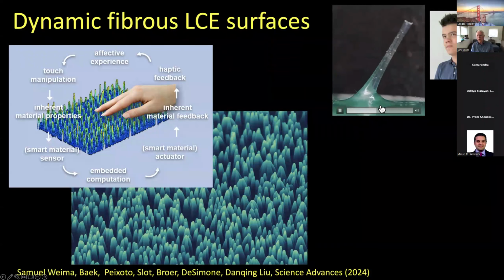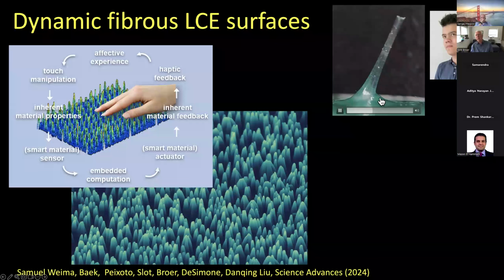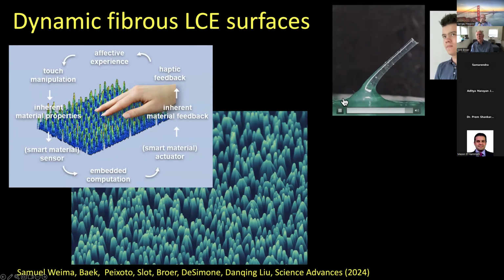In this case, we do it by heat. We have a small electrical heater in the foot of the fiber here, and then by heating it, the director is going from planar here to perpendicular here, so it gives the local change of position. But you can of course do it in other position, and then it moves to the other direction, and that is what Samuel Weima did in our group.